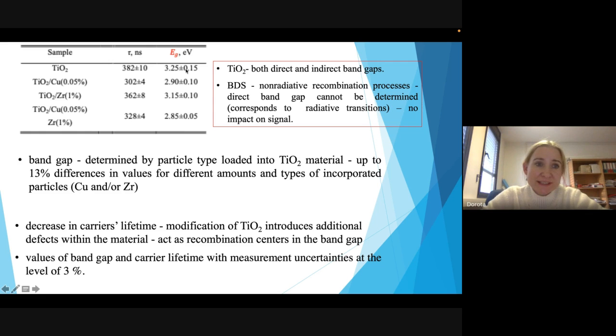Regarding the bandgap, generally after modification its value decreases by up to 13%, but it is strongly influenced or determined by the type and amount of particles incorporated into the structure. Regarding the carrier lifetimes, we can say that they also decreased. Why? Because by performing the modification, we introduced additional defects within the volume of the material that work as recombination centers in the bandgap. What is worth mentioning is that the uncertainty of determination by the use of this technique was at the level of 3%, which I think indicates that the precision is rather high.